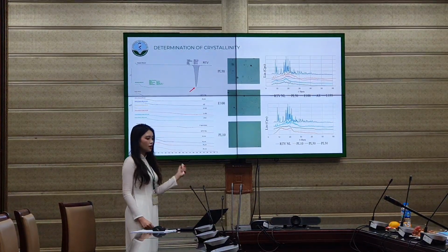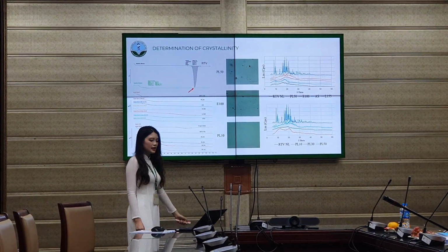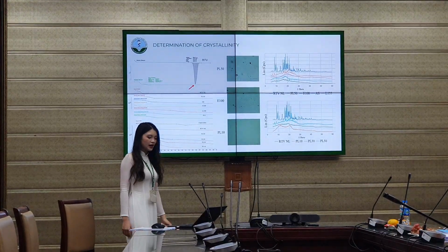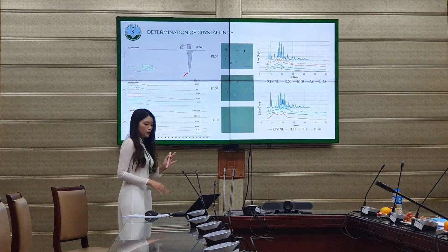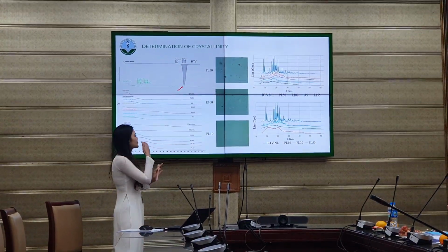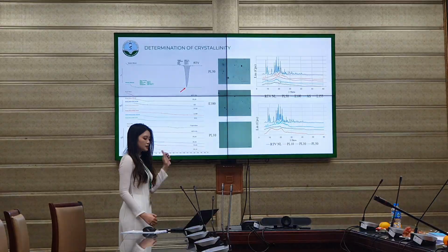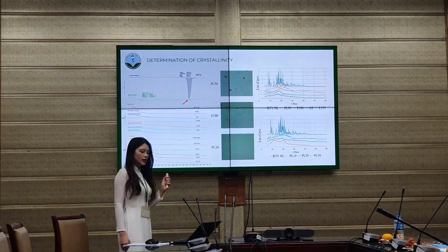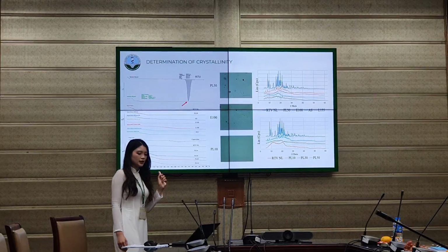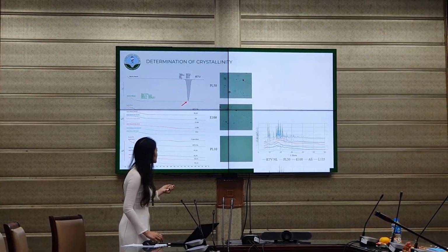The XRD results of the PL10, PL30, AS, and L155 samples exhibit no sharp peaks, proving that there is no crystal in these samples. But the PL50 and E100 samples still exhibited diffraction peaks, indicating the presence of crystalline phases. These results are similar to the microscopy results.